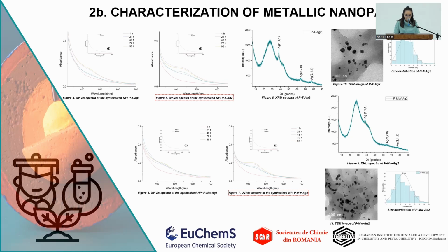Also, the total phenolic content of the samples was a very important aspect, because in the case of the ones synthesized with the microwave extract, they have exhibited a smaller crystallite size. Transmission electron microscopy was used to visualize the size and shape of the nanoparticles. The size distribution was determined by direct measurement of over 100 nanoparticles. And from the TEM images, their spherical or semi-spherical shapes can be observed.